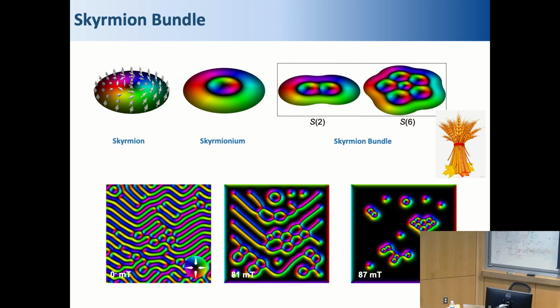We are interested in the skyrmionium that can freely move. So this is our prediction. If we again see this skyrmionium as the central skyrmion wrapped by a circular helix, if we see this circular helix as a bag, it should be able to contain more and more skyrmions inside. And this is what we call a skyrmion bundle. And this skyrmion bundle can really be realized.